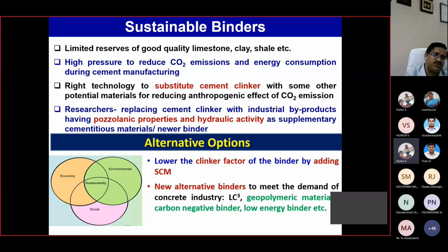Initially, in cement manufacturing, clinker is about 95 to 96% and 4% is gypsum. If you look at ordinary cement, the code has allowed performance enhancers by 5%, and a further 5% as admixtures of different types. So they can use pozzolanic materials about 10% in OPC, as per our revised IS 269 of 2015. The basic aim is to reduce the anthropogenic effect of CO2 emissions.